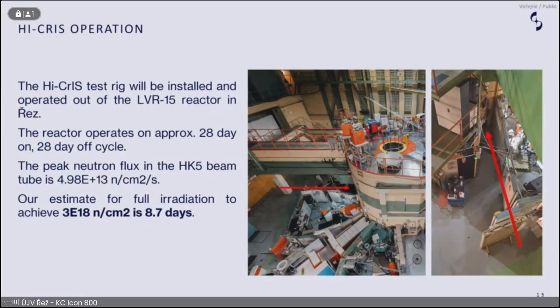3 times 10 to the 18 neutrons per centimetre squared, neutron fluence, in 8.7 days technically. But we don't get in for another 20-odd days, so we have to optimise this.